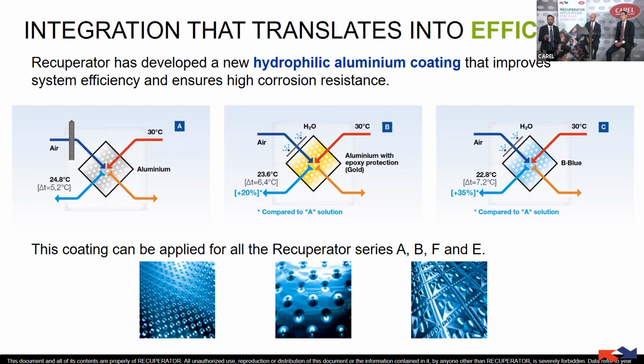In fact, with the first example, we reach like 5.2 degrees of difference in terms of temperature between inlet and outlet of the supply air. In the second case, if we replace the wet pad with the pressurized system, we can have a 20% increase of cooling capacity, and we can go even more thanks to the blue coating, this hydrophilic aluminium coating, that increases the cooling capacity even more, up to 35% compared to the first solution. So let's say again, pressurized system, humidification at the inlet, and the plate exchanger that should be completely wet. This coating, of course, can be applied to the whole range of heat exchangers in the Recuperator portfolio.